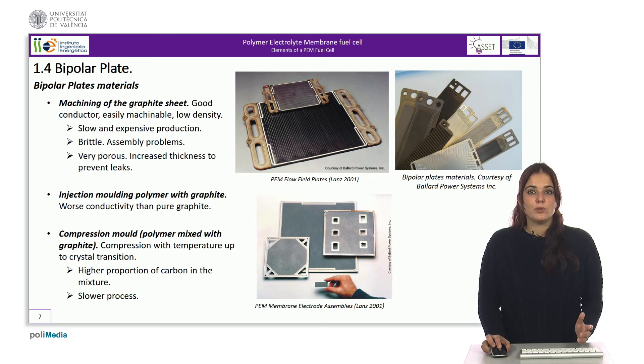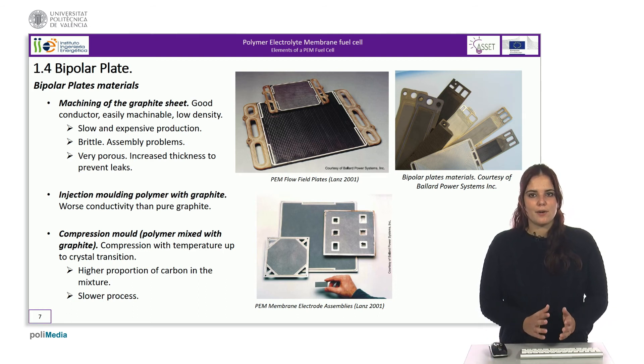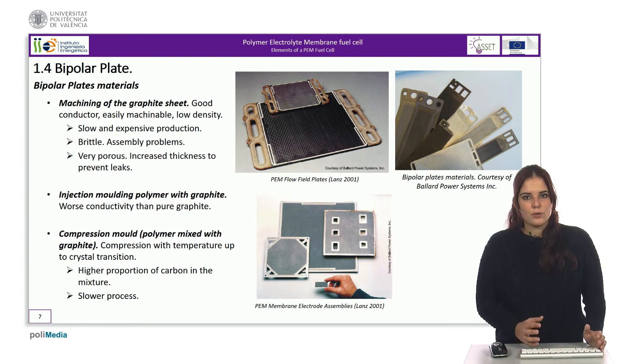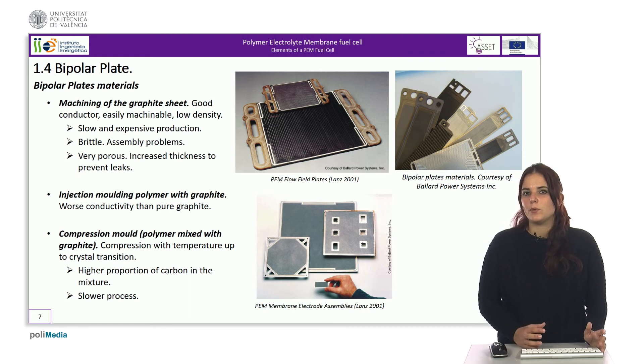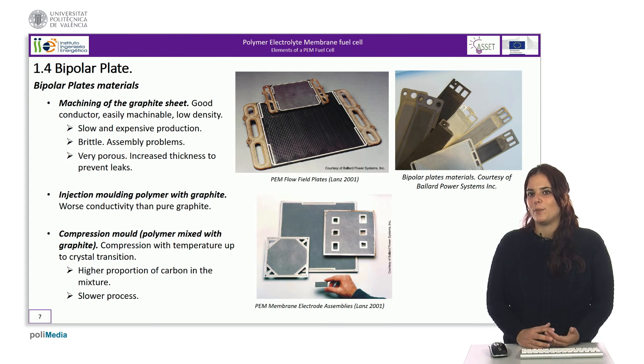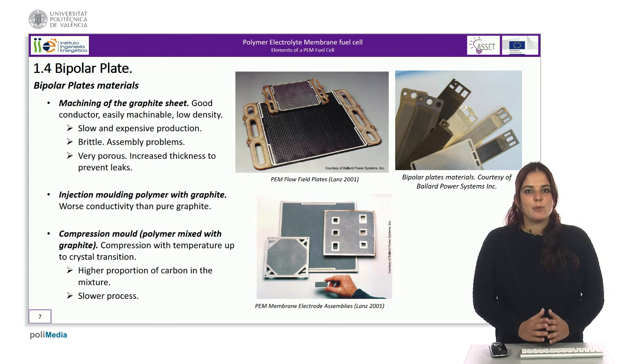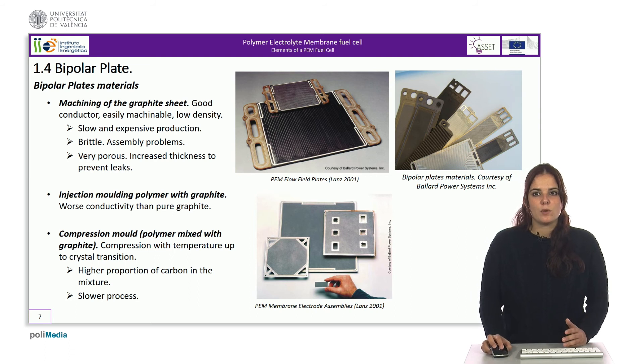Finally, a mixed solution is to use a mixture of polymer and graphite with a higher percentage of graphite. This allows the conductivity to be increased and the plate to be made by compression with temperature until the crystalline transition of the polymer is achieved. The process is slower than injection molding but it improves the conductivity.